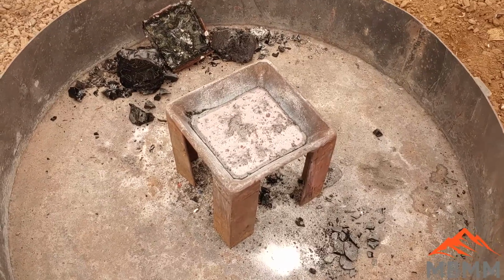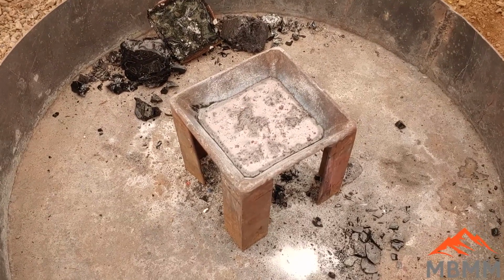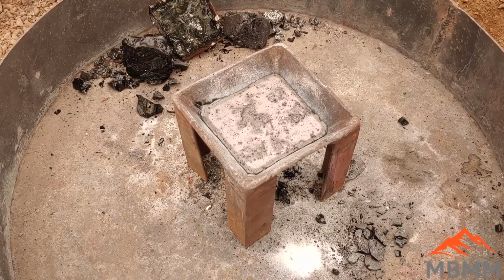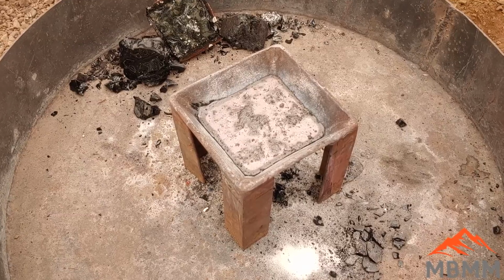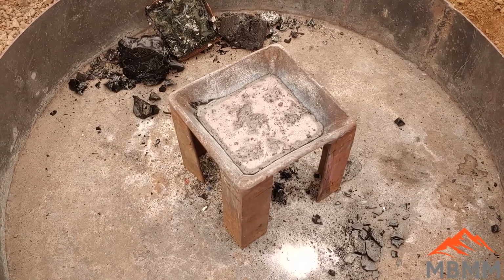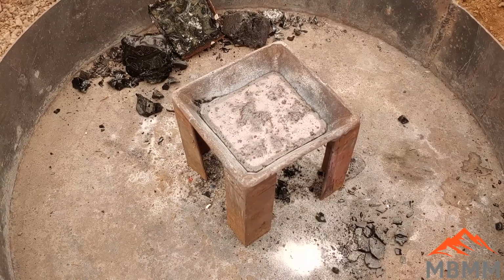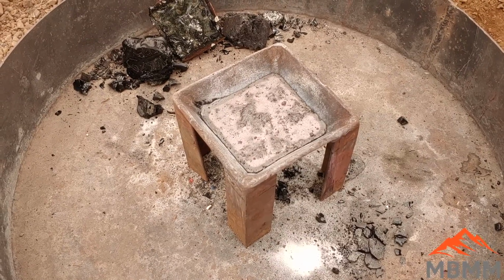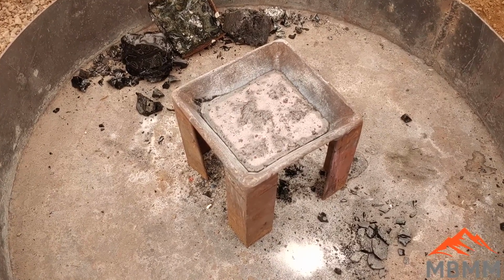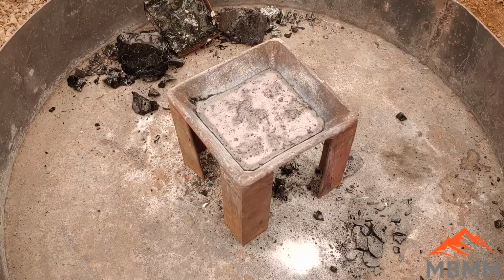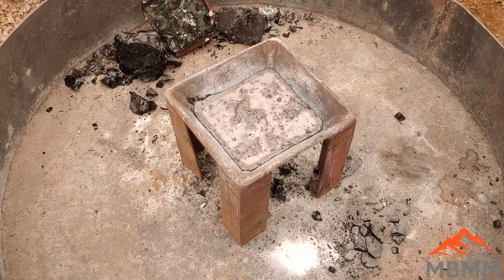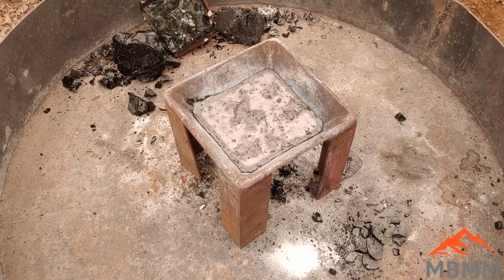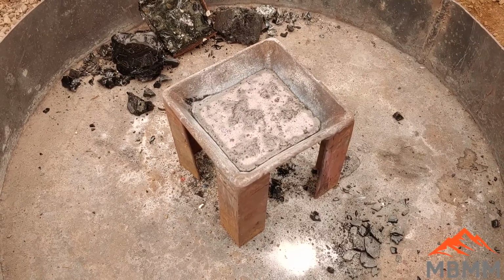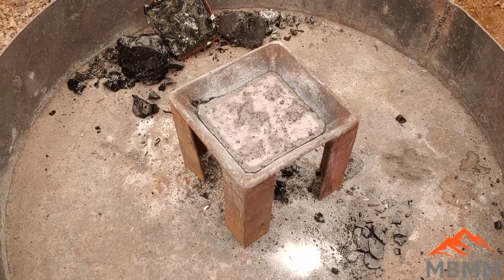Well, there's our pour from our graphite crucible, and it looks like the crucible held up a lot better to those sulfides and oxides than the fire clay ones. So we'll let that cool down a little bit and knock it off there. I added iron again. That seemed to get rid of the matte on the second pour. And so hopefully we should have a lead button, slag on top, no matte, and a good looking crucible.